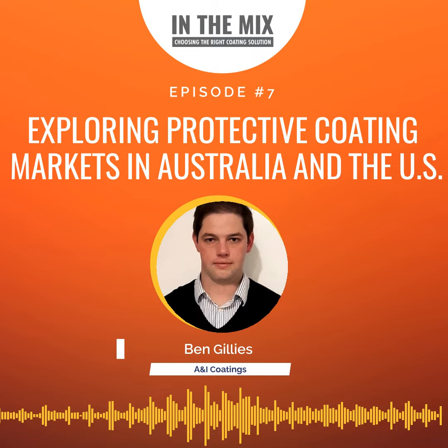So in the middle of Australia, for example, the UV is still very harsh. So if you've got feature architectural steelwork, which is red or yellow or orange or even black, it's still going to fade quickly, even though it's away from the coast, away from, I guess, those corrosion initiators. So we generally change the underlying coatings to suit the corrosivity category. But as a general rule, where budget allows, we'll stick to fluoropolymer for the top coat 99% of the time.